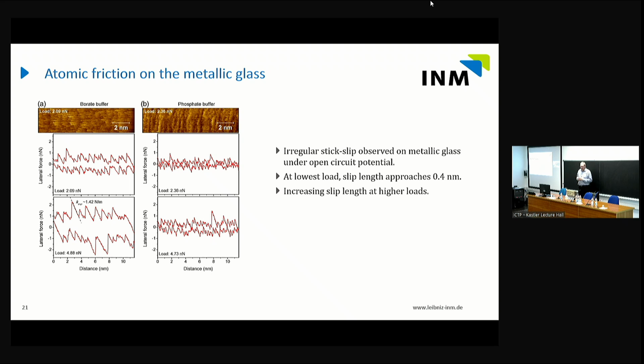Yeah? While on the phosphate buffer we have slips which are actually exactly at what these metallic glass people call the local cluster, which is at sort of clusters of 5 or so atoms, or maybe 8. So these are really 1 nanometer scale stick slips. So we have increasing slip length at higher loads.